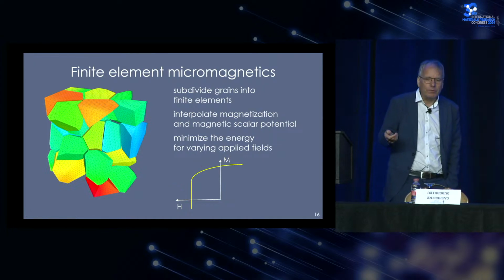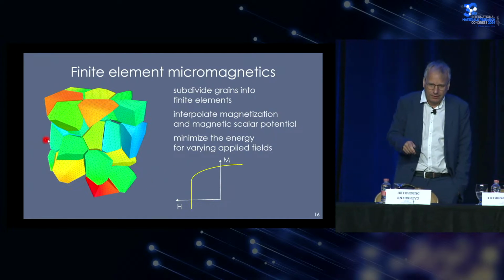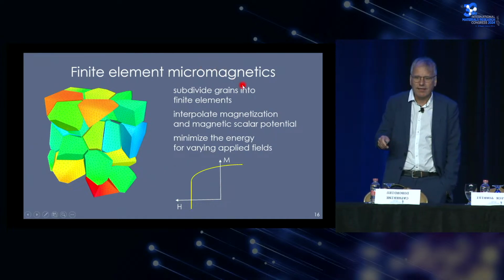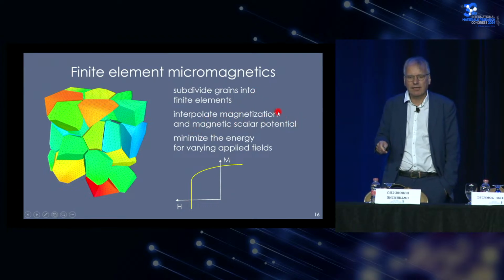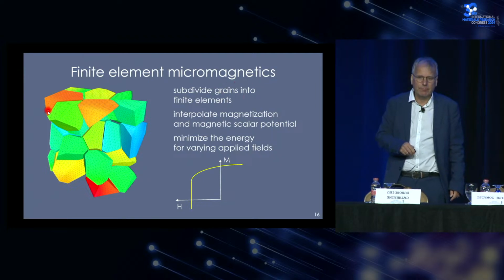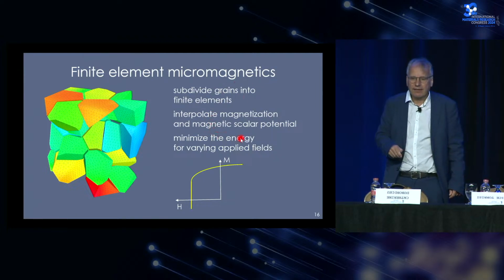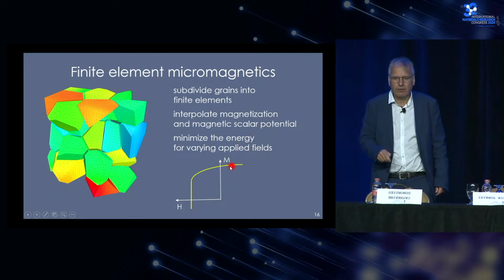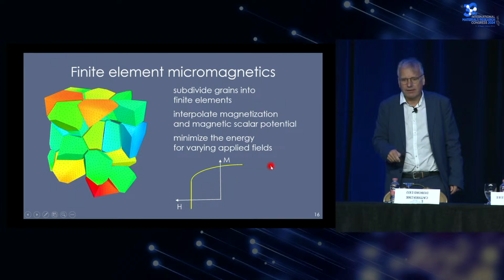So how do we do so? We subdivide the grains and the grain boundary phase into finite elements. We interpolate the magnetization vector and the magnetic scalar potential on this finite element grid. And then we minimize the total energy of the system for varying applied field, and we get the demagnetization curve.